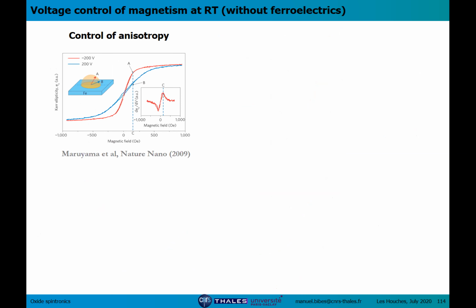However, I wanted to show you another batch of results, mostly from Japan, applying electric field through a dielectric to very thin layers of transition metals. So here, this is iron. I think this is one of the very first papers from Yoshishige Suzuki. They had iron and MgO, and they applied a large voltage across the MgO to accumulate charges into the iron. And as you can see, by doing that, they were able to switch the magnetic easy axis in the iron